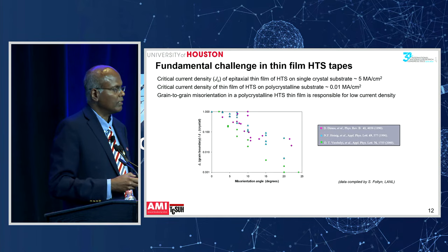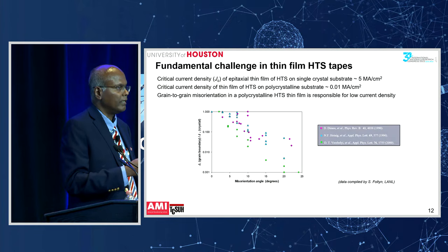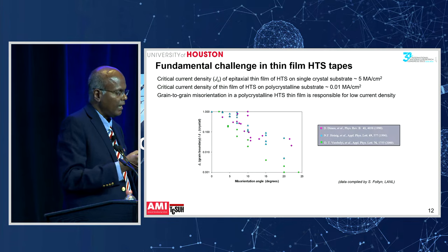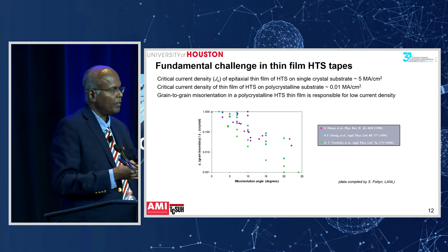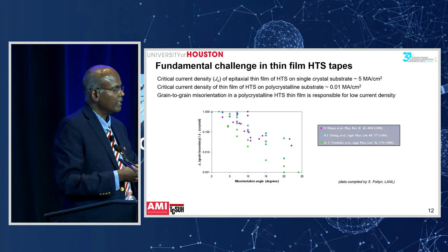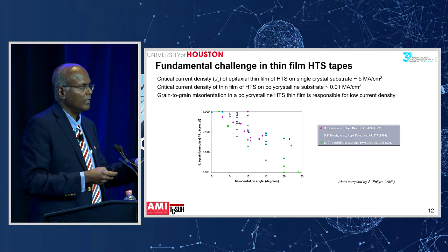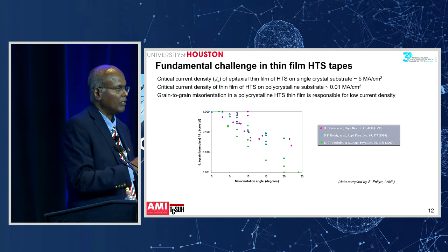This was recognized in some work that was done 25 or 30 years ago, where researchers took bicrystals, basically two single crystal substrates attached together, and deposited the superconducting film on top of that. So now you can measure the current across just one boundary, because you have two crystals with one boundary. You can see the current density across that boundary in the graph, and it's a log scale. When the grain boundary misorientation angle exceeds 10 degrees or even 5 degrees, the current density across one boundary drops by orders of magnitude.